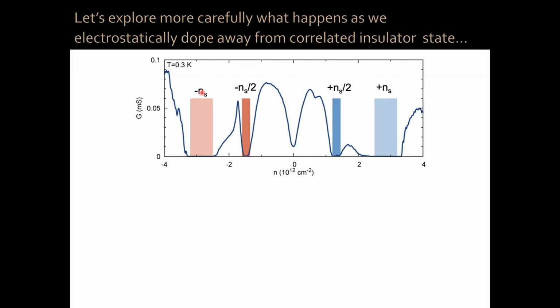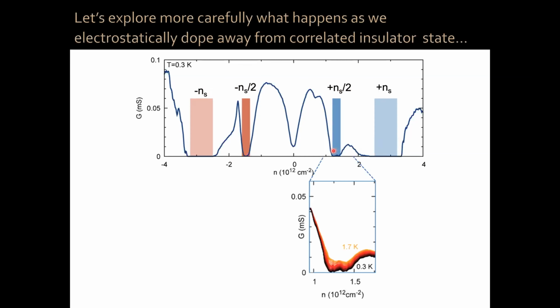Now, as we were looking at these data, we were doing temperature dependence, okay? When we looked at the temperature dependence of the conductance around the correlated insulator for electrons, these are traces at different temperatures from 1.7 Kelvin to 0.3 Kelvin. We saw that the colder we went, the lower the conductance was. That is what is expected of an insulator. When you cool down an insulator, it conducts less and less the colder you go, because there's less and less thermal energy for electrons to get activated across the band gap, okay?